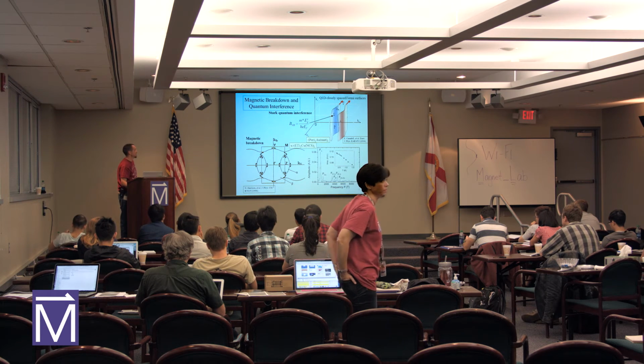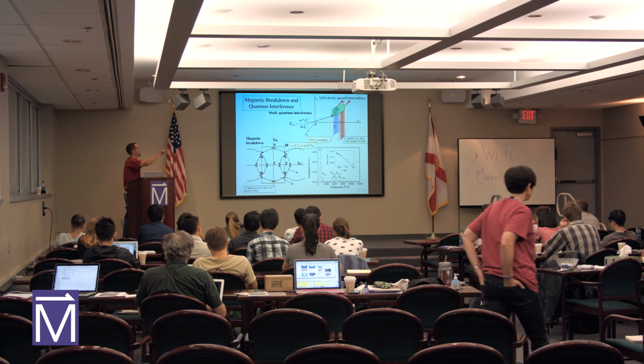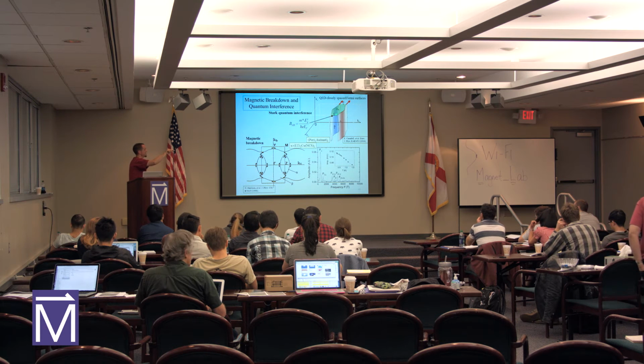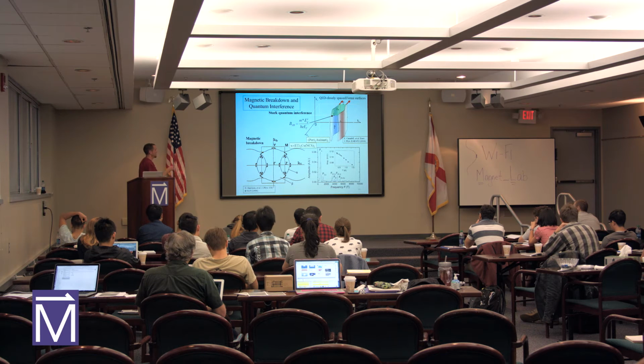And even though this isn't a closed Fermi surface, an orbit can't go around it, because the carriers interfere, you'll see oscillations in the data from this green space shown here. And if you rotated the sample, you'd actually see the same kind of angle dependence you see in other samples as well. But this isn't a quantum oscillation. This is what we call quantum interference. The carriers interfere when the Fermi surface is closely spaced.